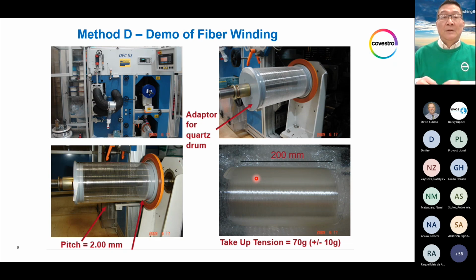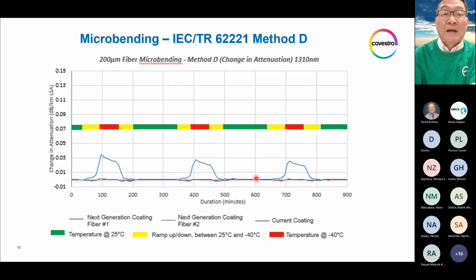In this particular paper and innovation, we also intentionally conducted the microbending test with method D. On top of method D, we also performed the test in a temperature cycling fashion, because we realize not only the microbending, but more specifically low temperature microbending, is more essential to winter month performance of the optical network when fibers are in the cable.